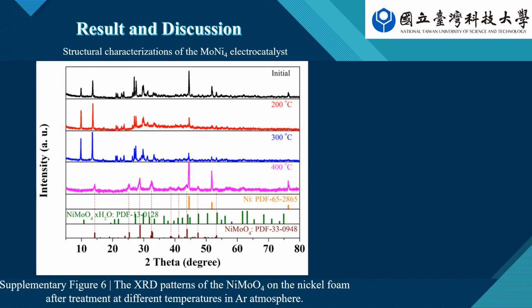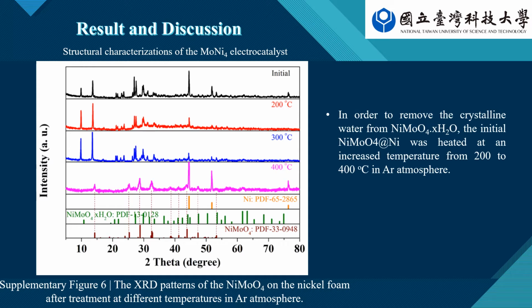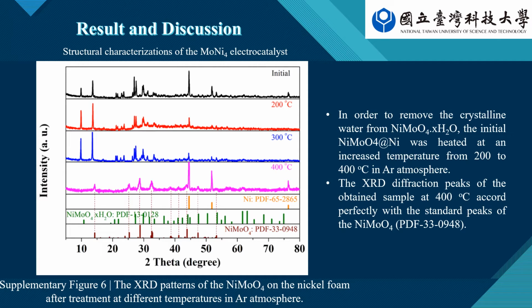Results and discussion: structural characterization of the MoNi4 electrocatalyst. I took this figure from the supplementary document. In order to remove the crystalline water from nickel molybdenum oxide, the initial sample was heated, increasing the temperature from 200 to 400 in argon atmosphere. We can see from the XRD that the diffraction peaks of the sample obtained at 400 degrees Celsius accord perfectly with the standard peaks of nickel molybdenum oxide, NiMoO4, PDF 33-0948.